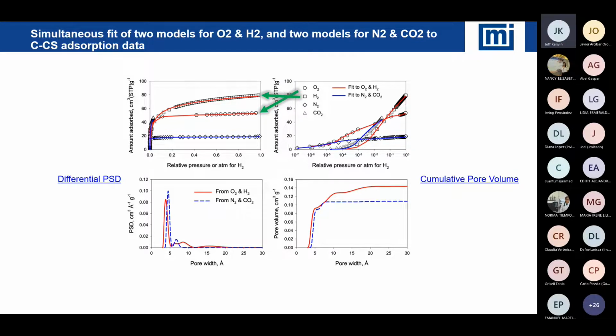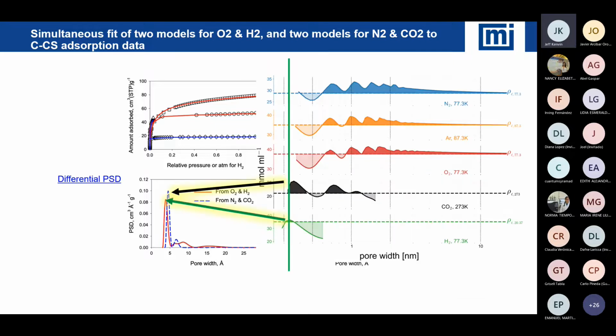So the range of gases that are required for full characterization is becoming more challenging. Okay? This effect, again, gets back to being able to use a smaller molecule like hydrogen, and that smaller molecule does give us perhaps a much better picture of the material and the true pore size distribution associated with that material. But again, when we look at what's happening in adsorption and characterization, the science behind it is being driven heavily by high quality adsorption data and high quality modeling. The two of them are coming together very nicely.